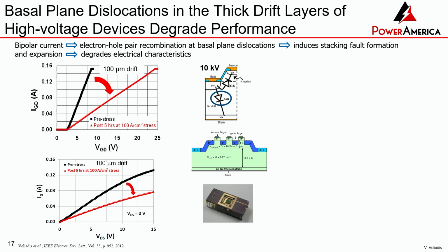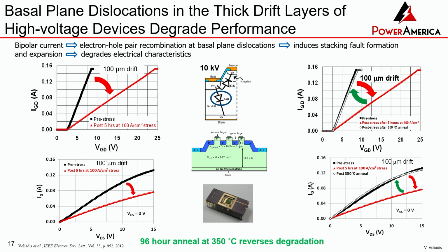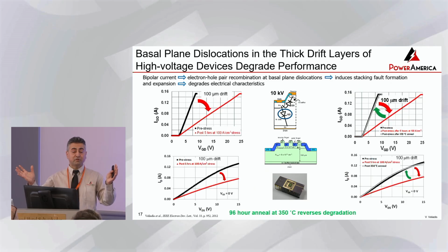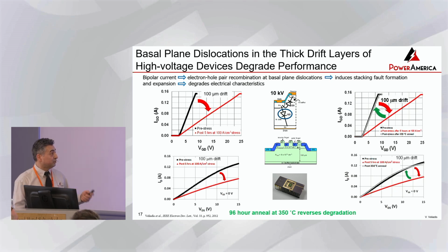Another big item with silicon carbide are basal plane dislocations, right, which under electron hole recombination will lead to stacking fault expansion. And you can see here, this is back from 2010 or so, 100 micron device. And as soon as you turn the gate to drain diode on, in the presence of BPDs, you have this drop, and the device is a catastrophic type of defect, right? The performance degrades drastically. And I had shown in those days that by annealing this transistor at 350 degrees, you're able to take it back to its original state. So the BPDs find the energy to expand into stacking faults, and then the stacking faults under anneal shrink back to their original state. But anyway, BPDs and the stacking faults are an issue when it comes to high voltage devices. So that's something to keep in mind.